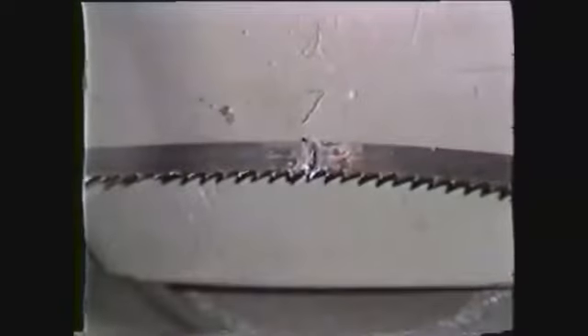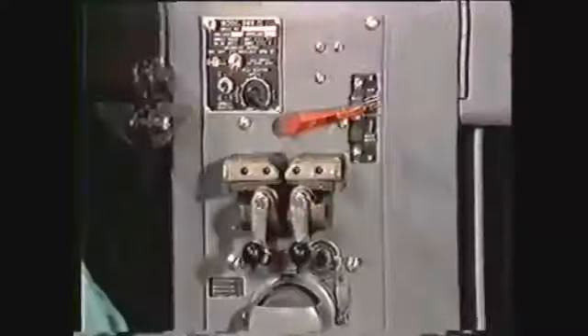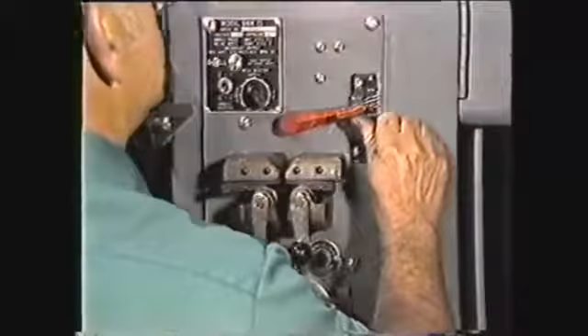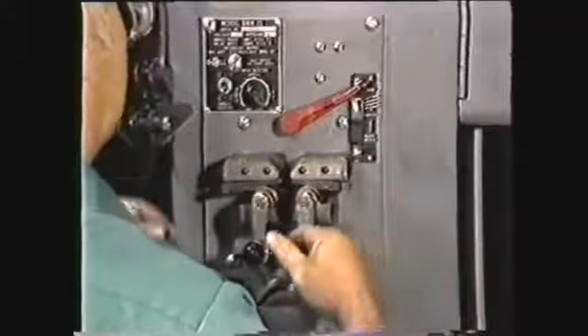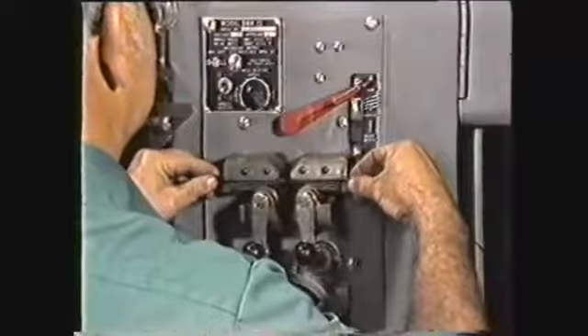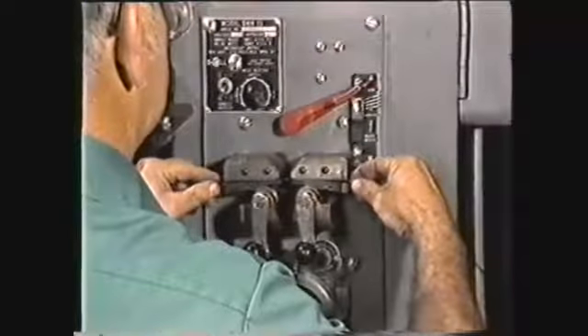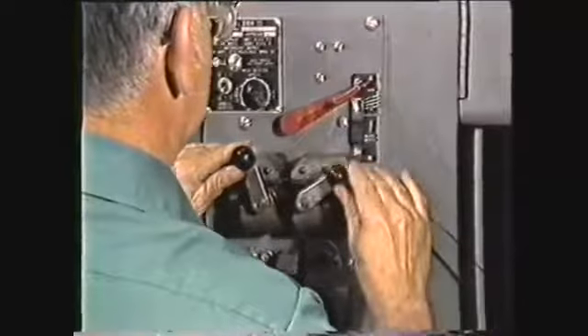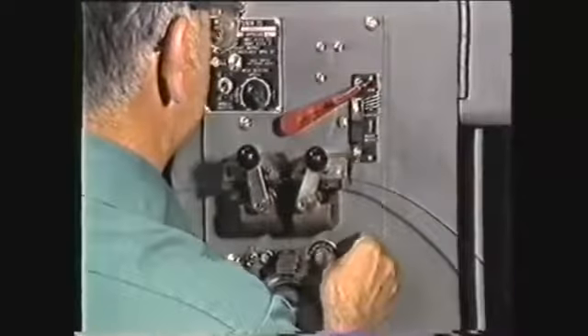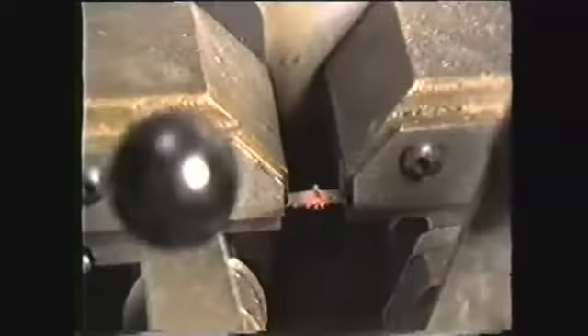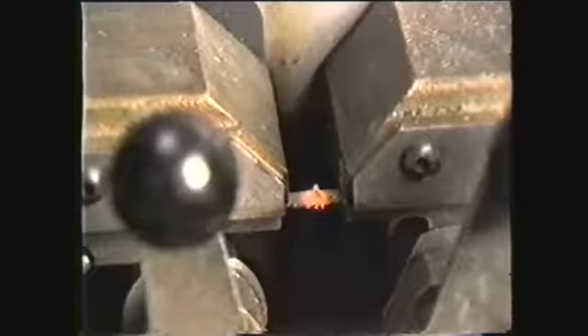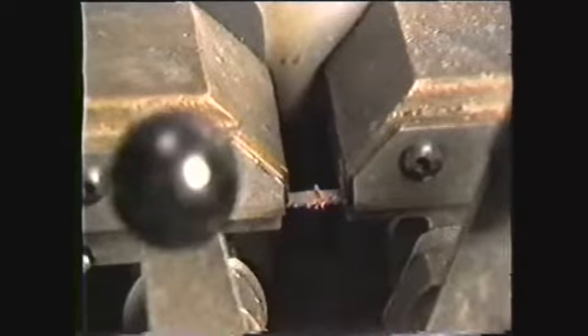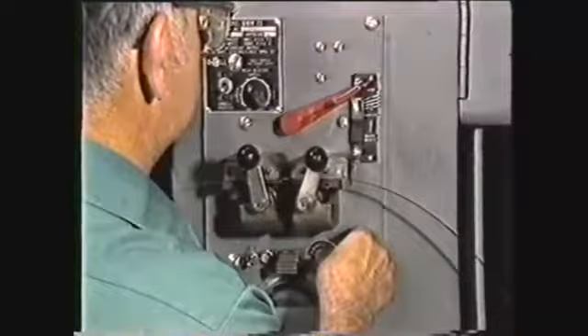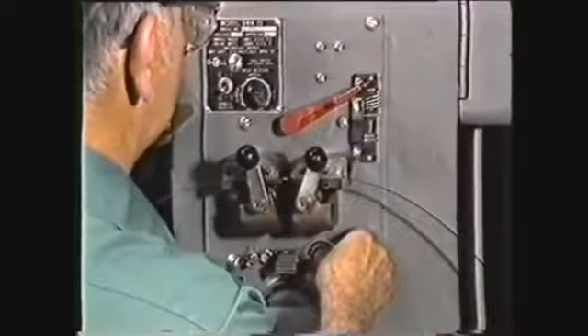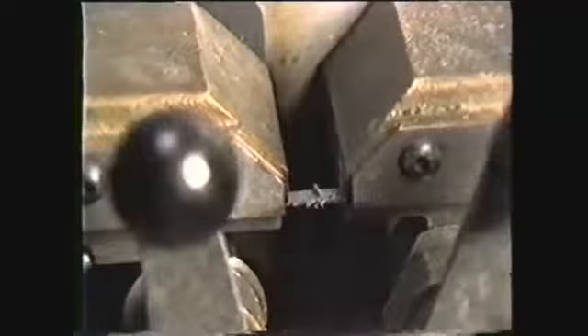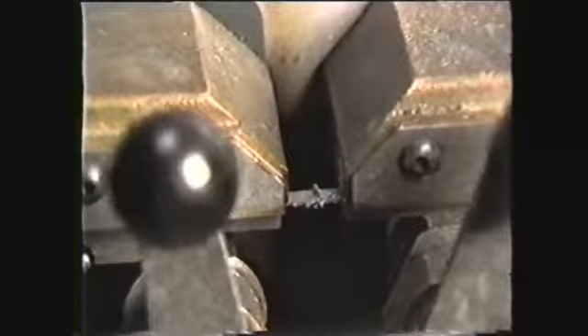It is best to anneal the weld area before grinding. Set the weld lever to anneal and reclamp the blade in the front of the jaws. Then, depress the annealing switch and keep it depressed until the welded area reaches a dull red. Then slowly cool the weld area by releasing and depressing the annealing switch until the dull red color has disappeared from the weld area.